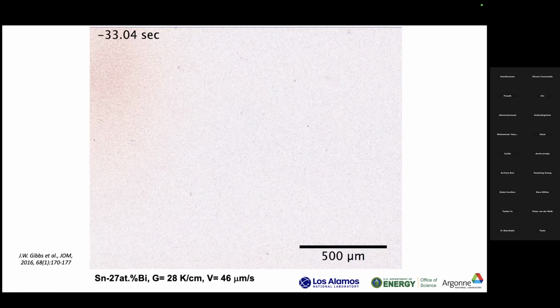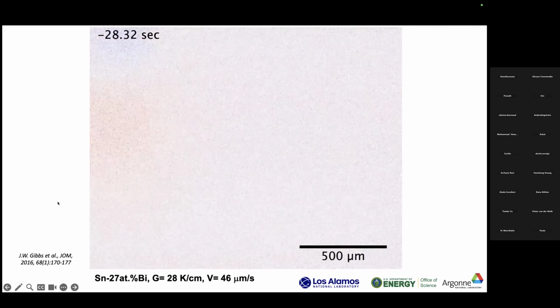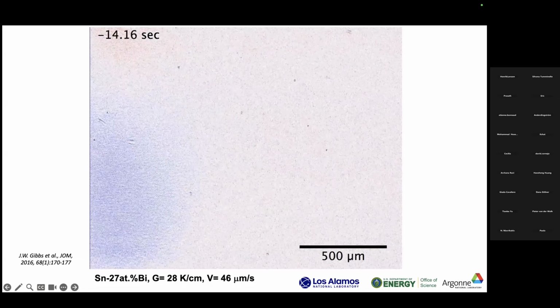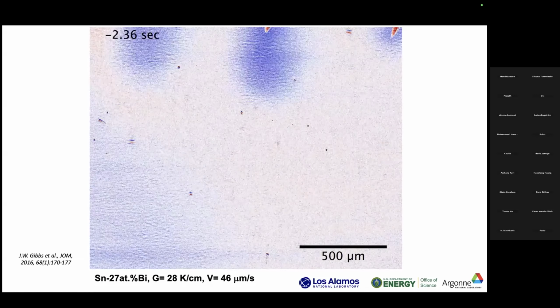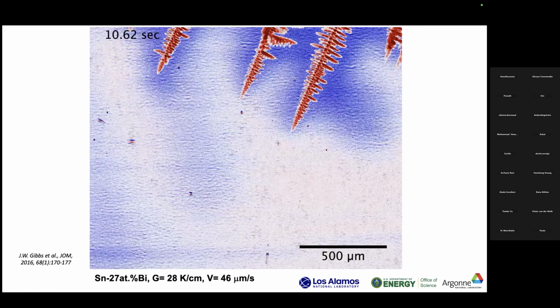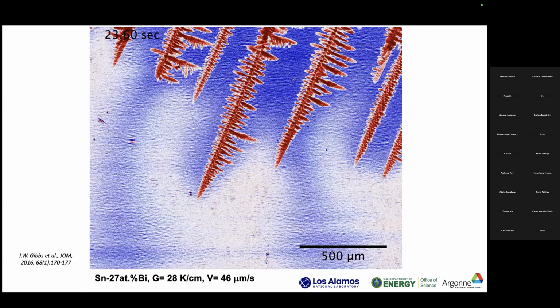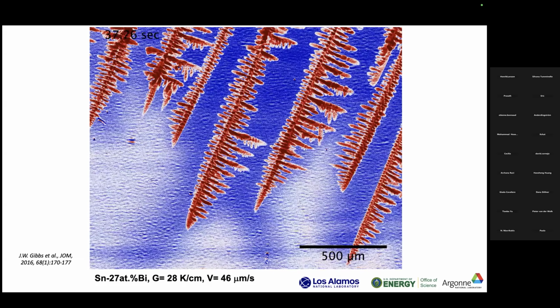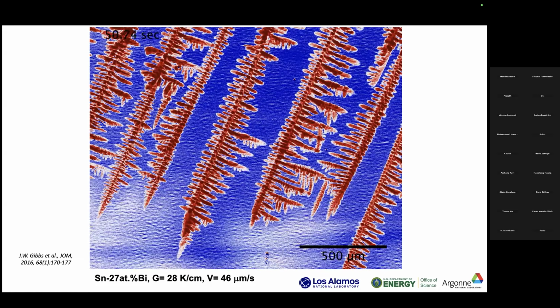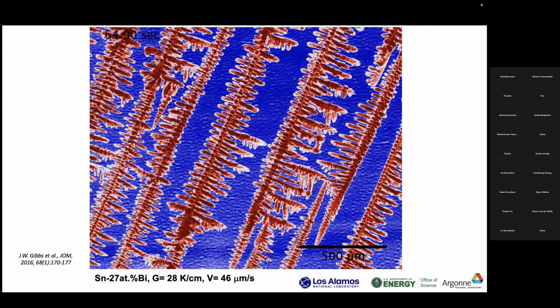So you're going to see tin-rich dendrites sweep into the field of view. And then you're going to see the bismuth solute, which is colored blue, I believe, kind of falling in plumes in the melt. And you'll see sort of the enhanced effect of gravity here. So here comes the array, which I think is colored red. And then you see the blue bismuth solute, again, falling in plumes. The bismuth solute is higher density, right? So we're kind of taking advantage of the enhanced effect of gravity here.